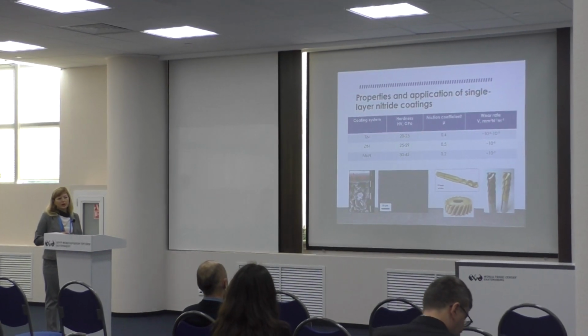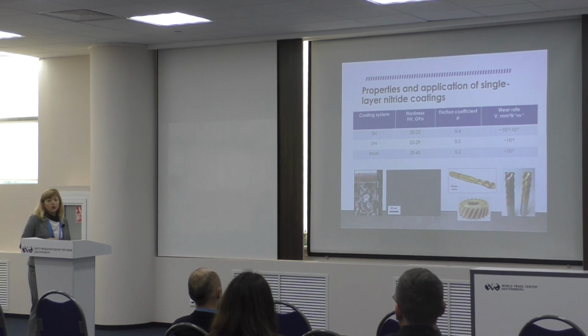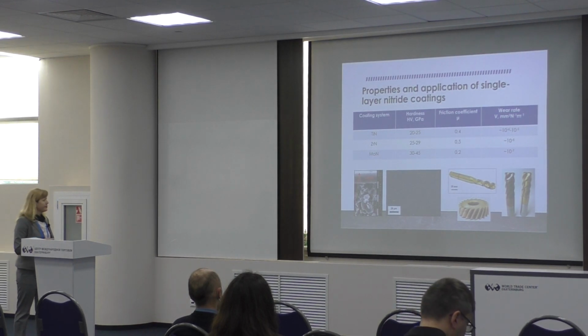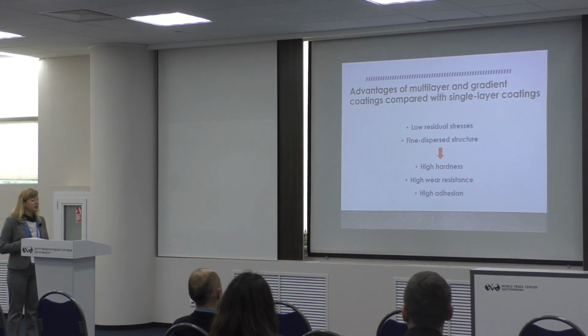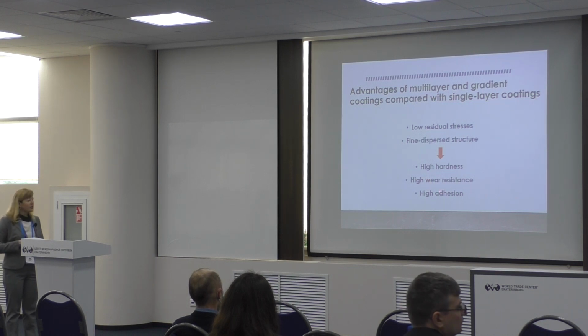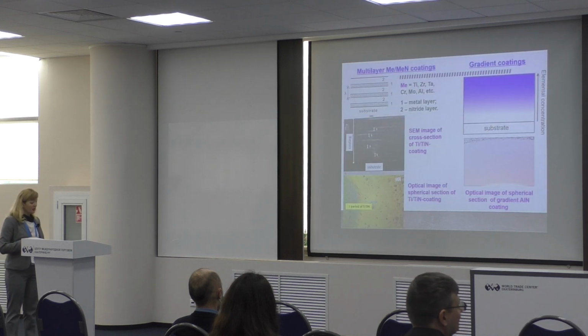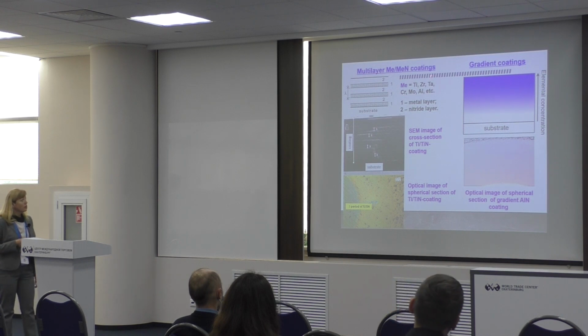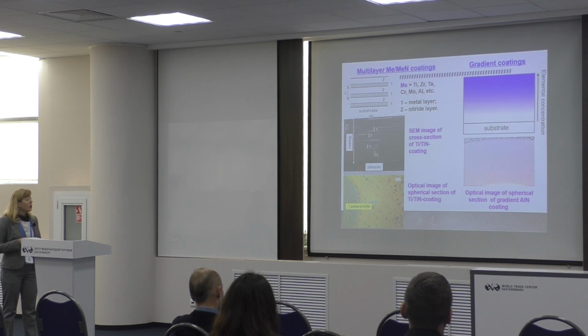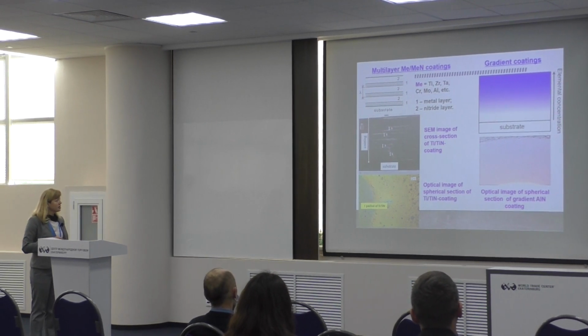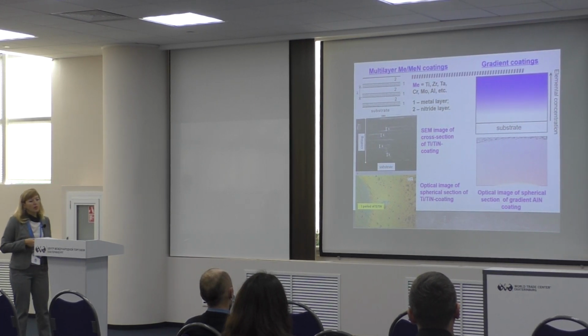One of the ways to solve this problem is to change the structure to multi-layered or gradient. The advantages of multi-layered gradient coatings compared with single-layer coatings are low residual stresses, fine dispersed structure, high hardness, high wear resistance, high adhesion, and other improved properties. We can deposit multi-layered coatings of metal nitride type, where metal and metal nitride alternating layers have thickness from units of nanometers to hundreds of nanometers. You can see examples of titanium nitride multi-layered coatings.